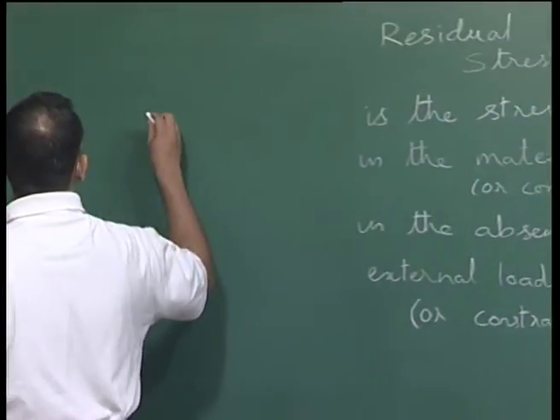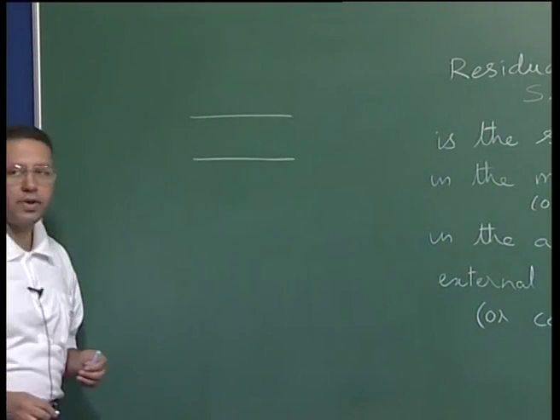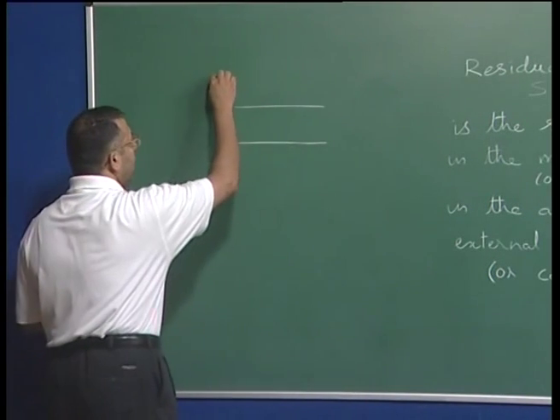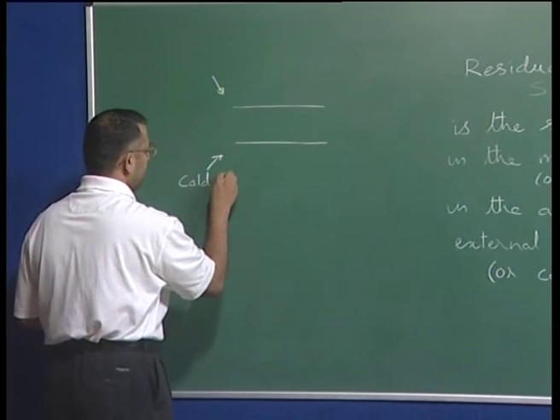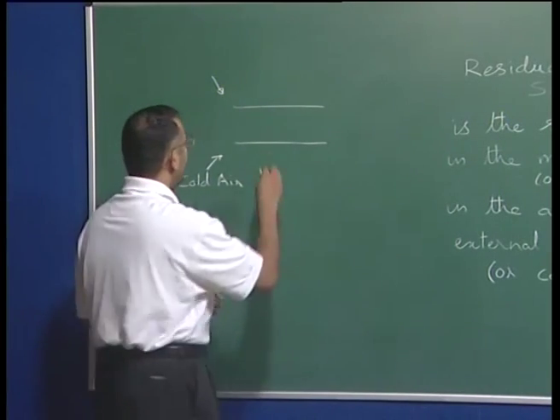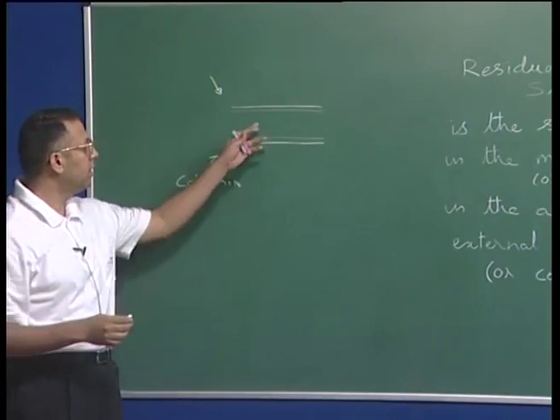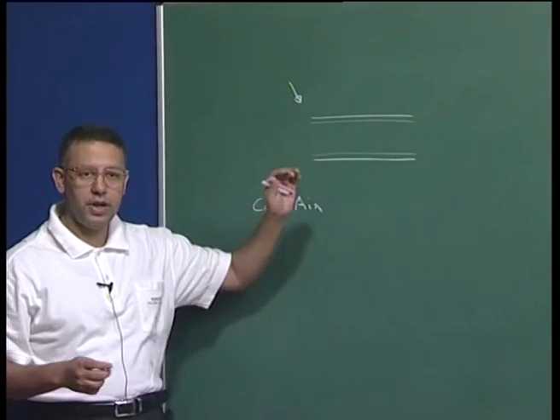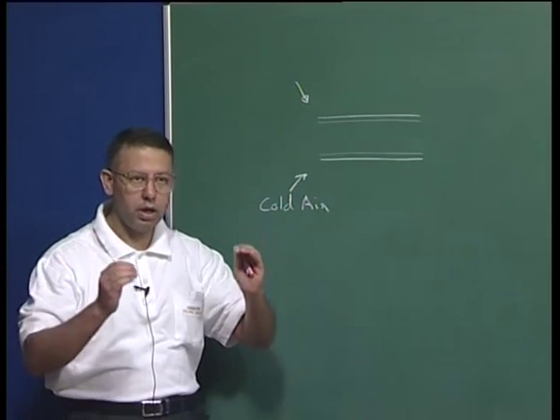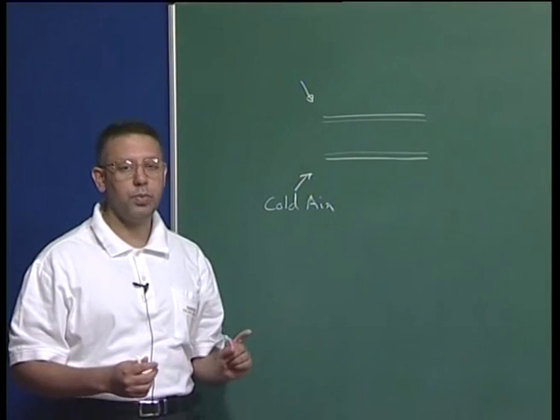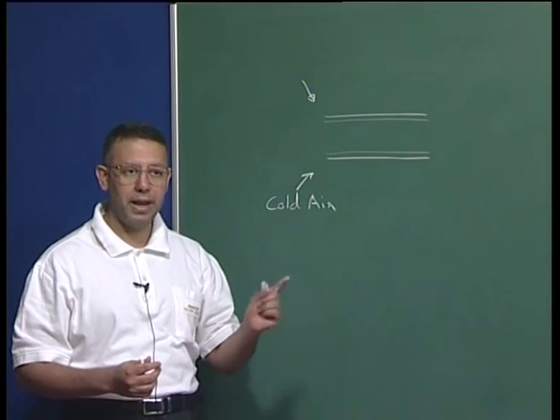Let me give a trivial example. Suppose I have a cross-section of a slab of glass which I want to toughen. While solidifying the glass, I will blow cold air from both sides on the top surface. What will happen is that the surface will solidify first — I am drawing a small solidified layer on the surface — and later the inner region solidifies. When the inner region solidifies, the glass contracts and pulls the surface inward, introducing compressive stresses on the surface. But for the body to be in equilibrium, the surface compressive stress has to be balanced by tensile stresses within the body.